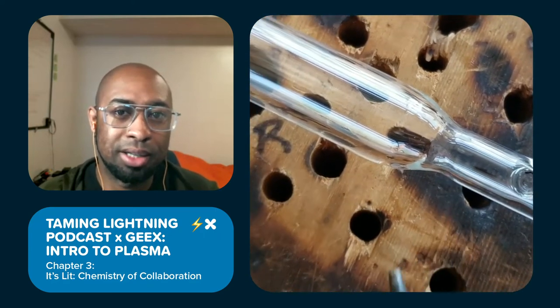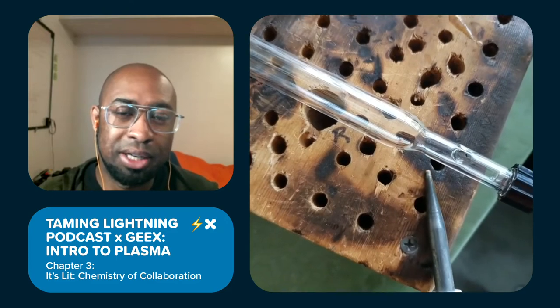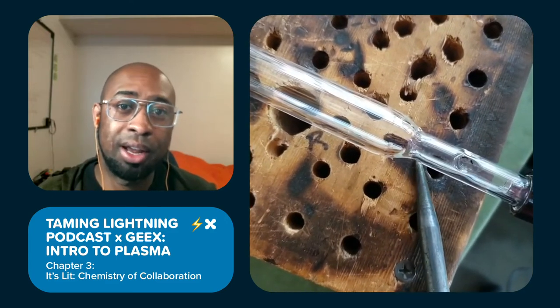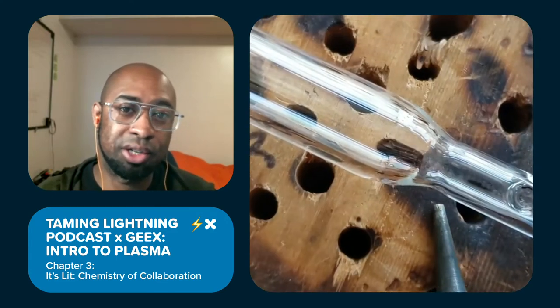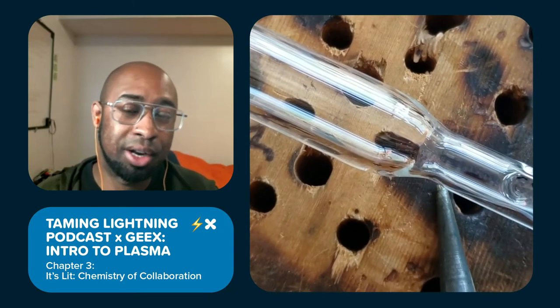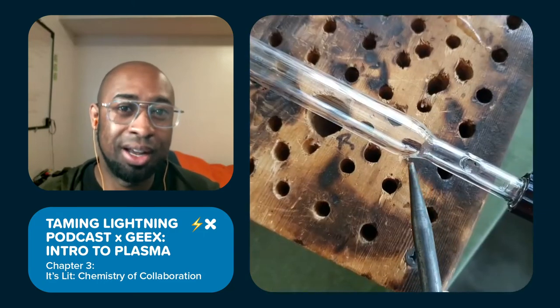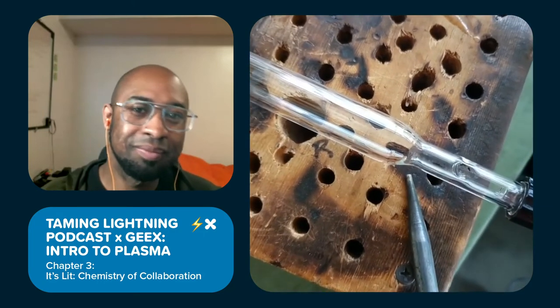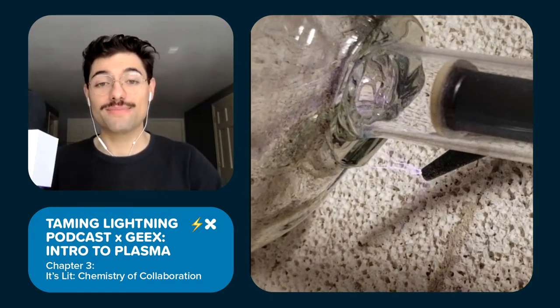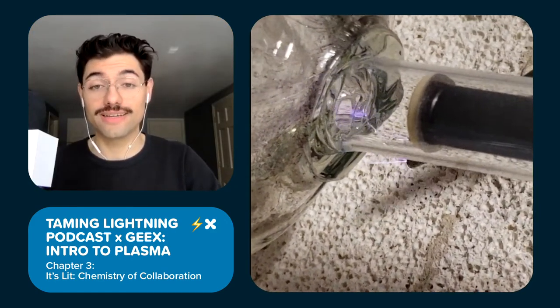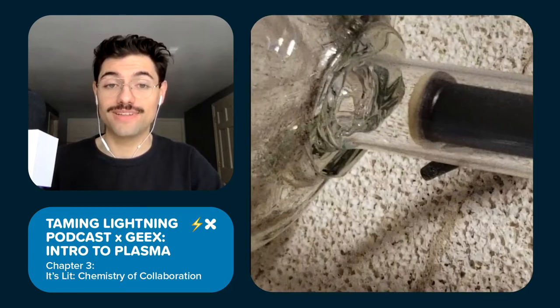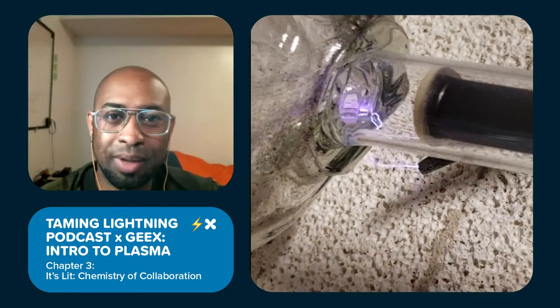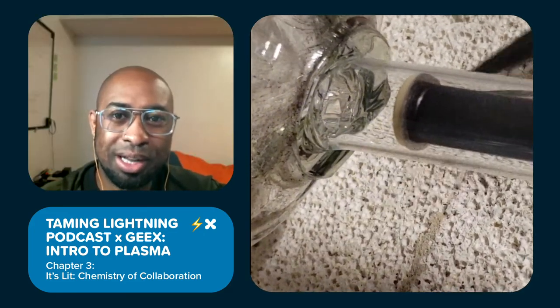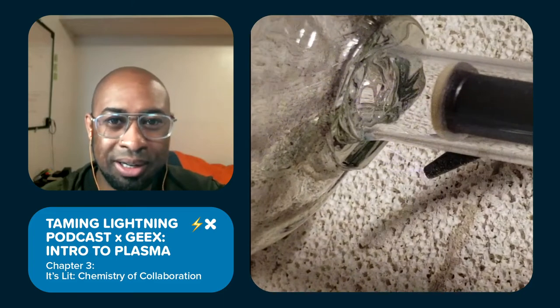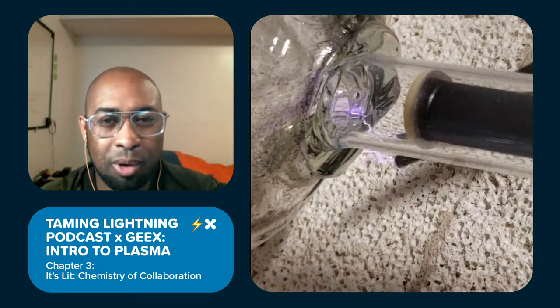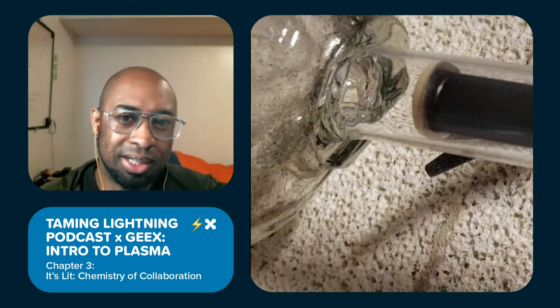Good point to make here is that you don't want to point the tip of your spark coil towards any part of the surface that you're searching. This will create a concentrated spot which could introduce leaks instead of finding them. And with that, if the spark locates on a single point, then you may have a small leak. Exactly. And if it's soft glass, it's most likely time to start over. But it can be reworked, depending on where the leak is at.